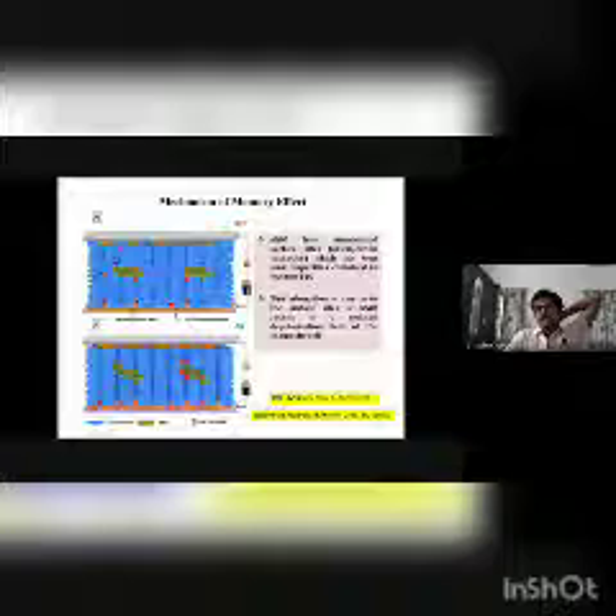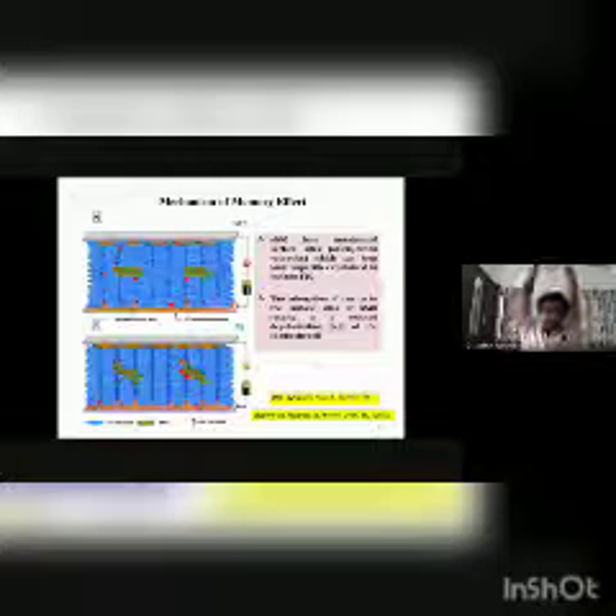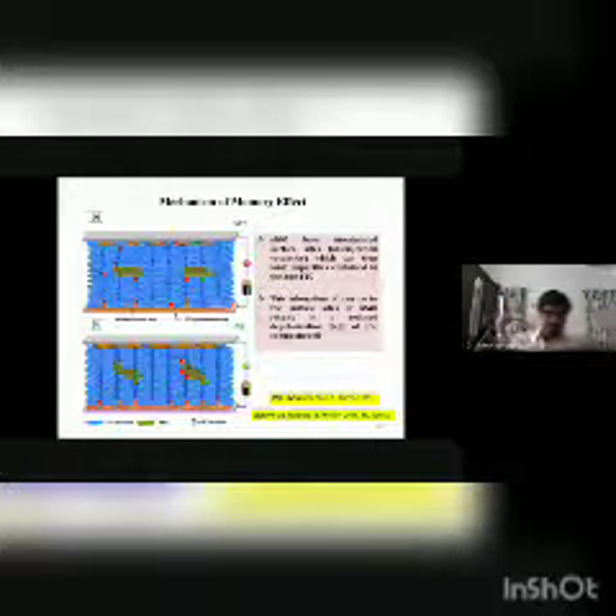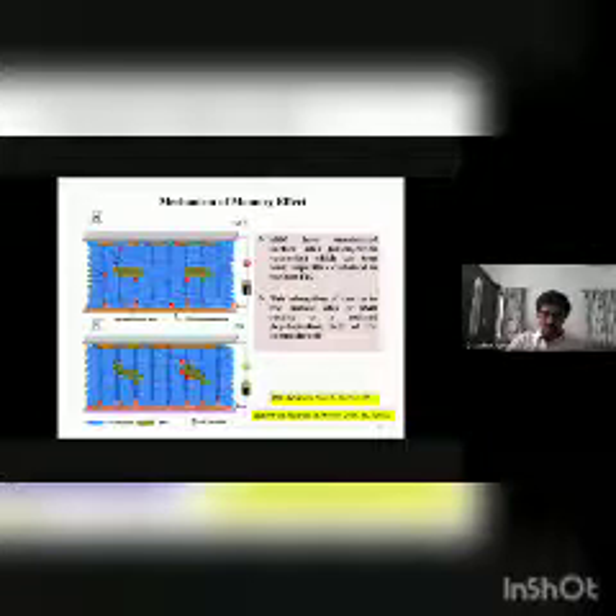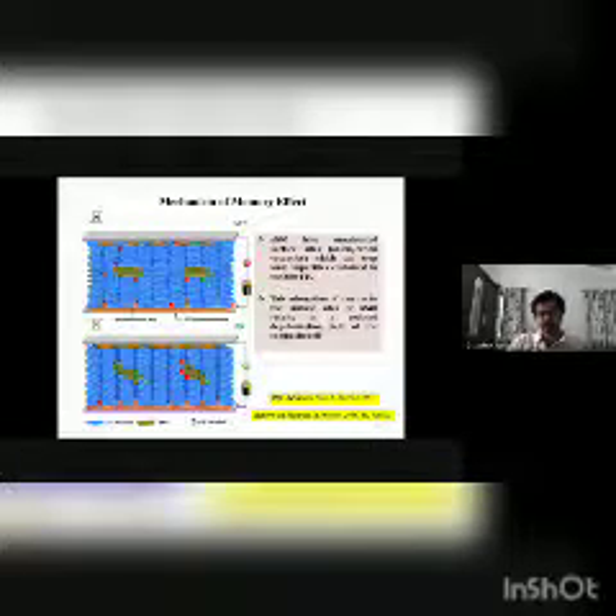So we have elucidated a model from these observations, and we found that it is because of trapping of impurity ions onto the surface of the nanomaterial. These are the nanomaterials, this blue color is the FLC molecule, and red and green are impurity ions. So when you are switching it, these impurity ions travel to the opposite electrodes, and while traveling, they may get trapped on the unsaturated surface sites of the nickel nanorods.